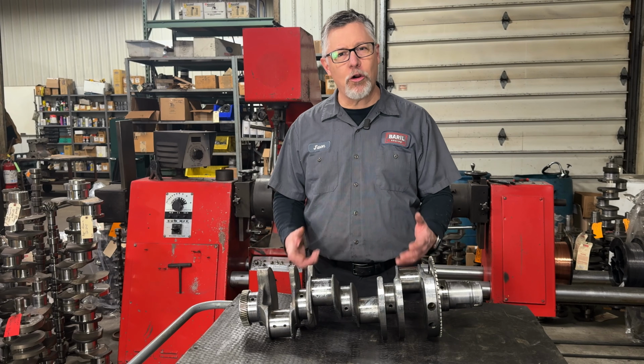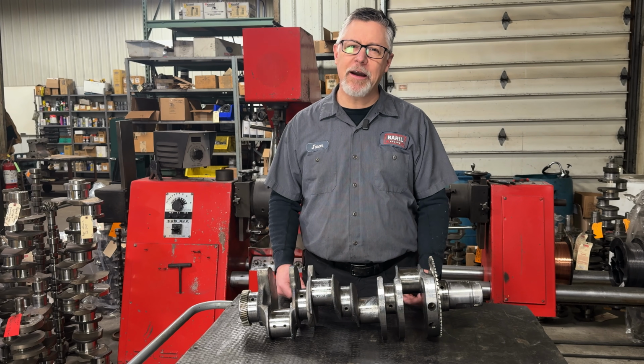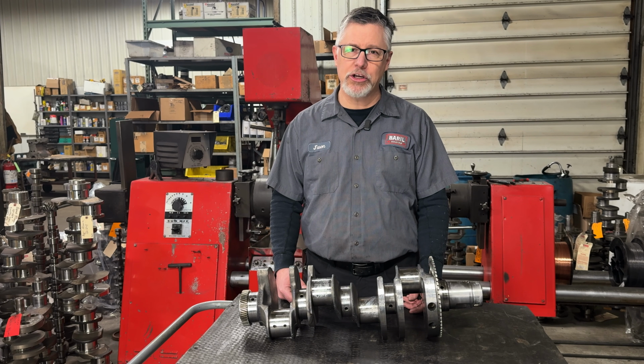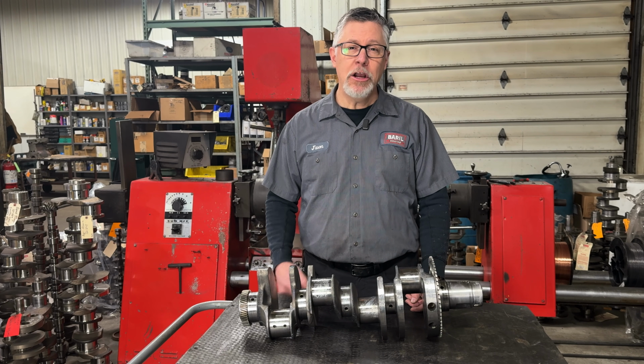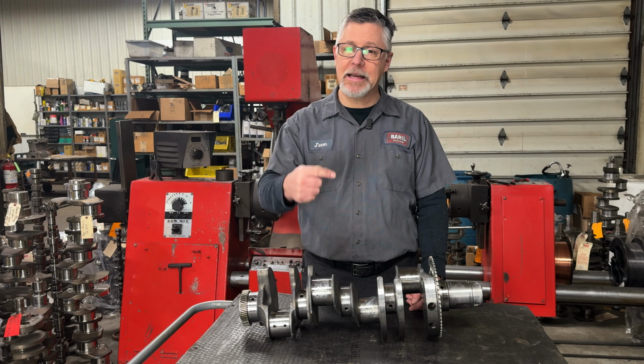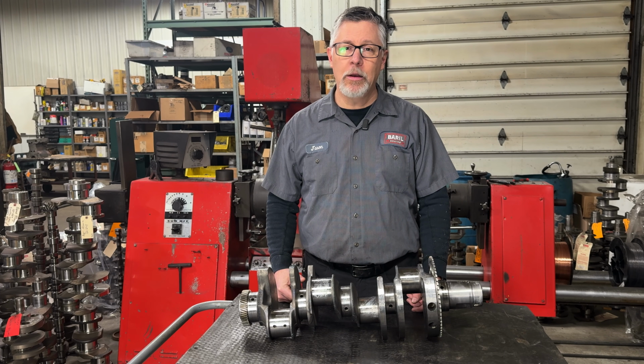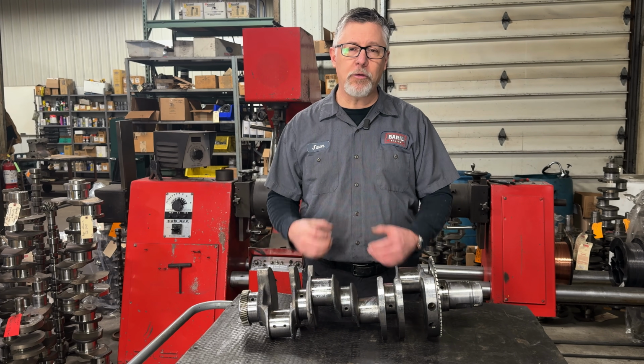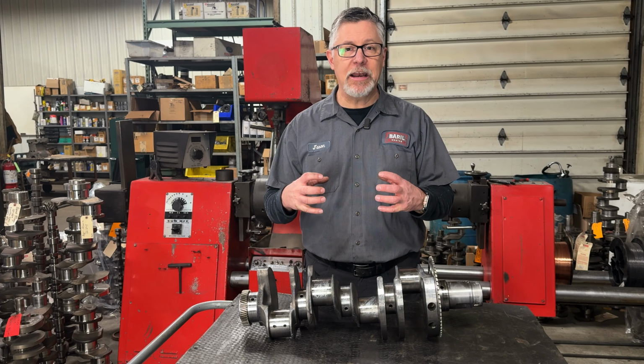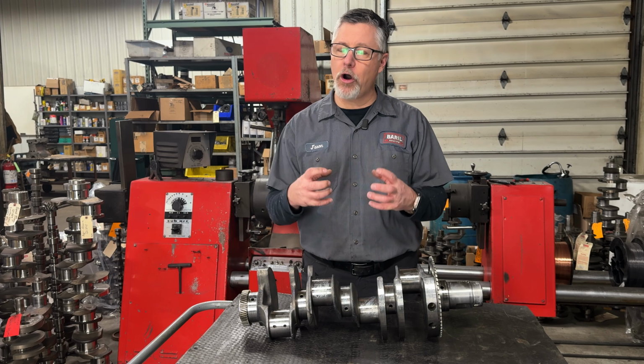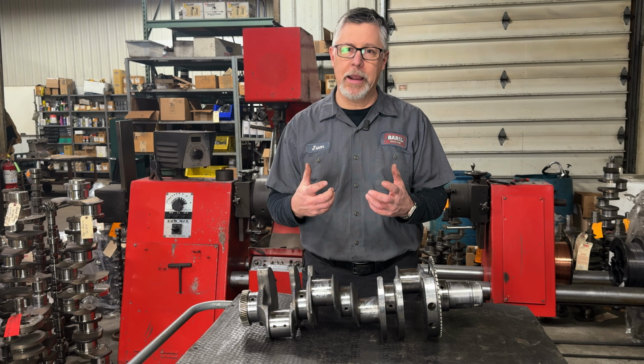Before we get into our crankshaft welding project, let me cover some things we can't do with a crankshaft welder, or at least not do very well. One would be to repair a broken crankshaft. The reason is, while we could get it to stick together with a weld around it, we're never going to be able to get that weld through the material enough to give it enough strength where a crankshaft with all the stress that goes through wouldn't break.